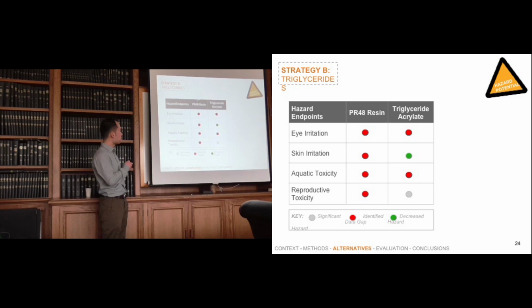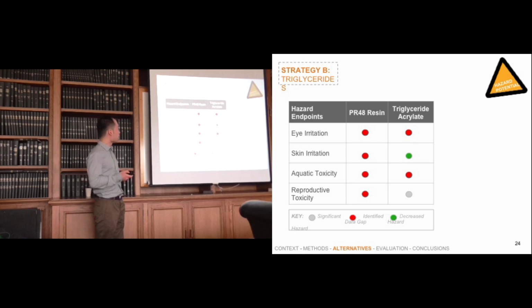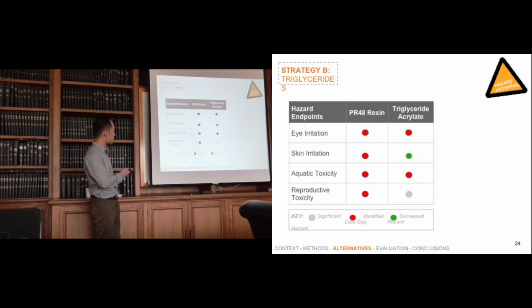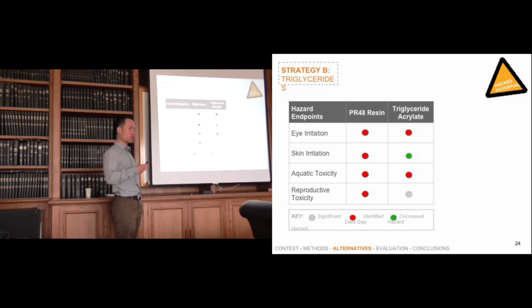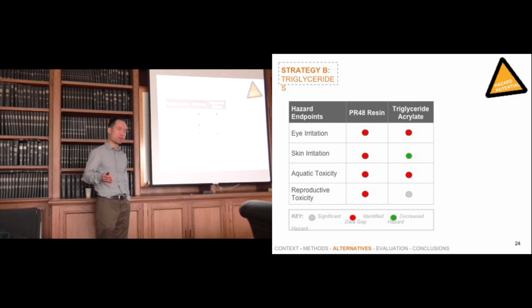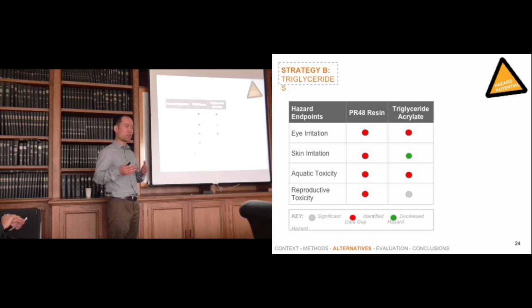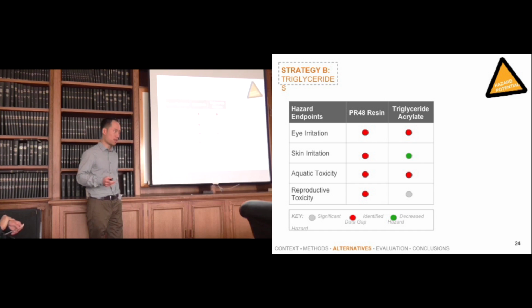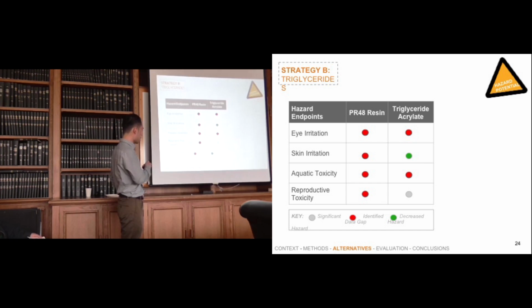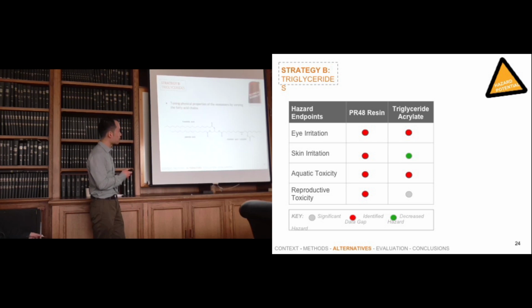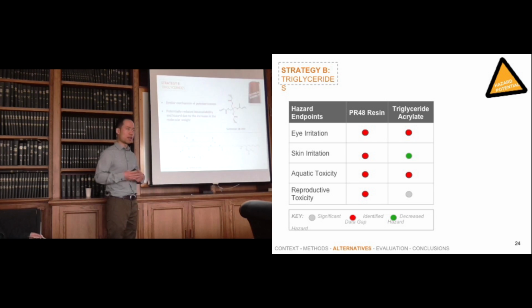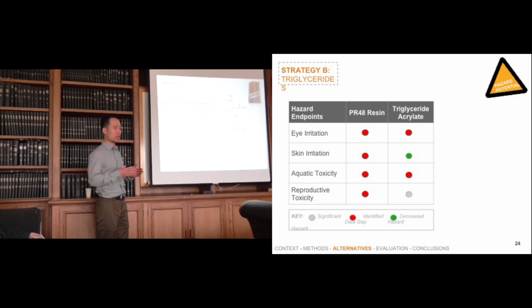So compared to the PR48 resin, we believe that due to the decreased bioavailability, it should pose at least a decrease in skin irritation, if not improvement in the other criteria we evaluated. And just to mention that because the triglycerides are sourced from nature, it is biorenewable and biodegradable, because those are natural substrates for bacteria as a food source. So comparing that to the current resin material, that is also a very nice feature to have, even though it's not directly geared towards making a safer material.